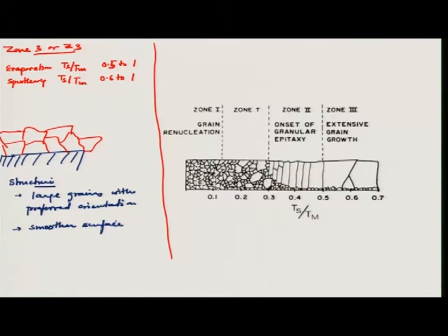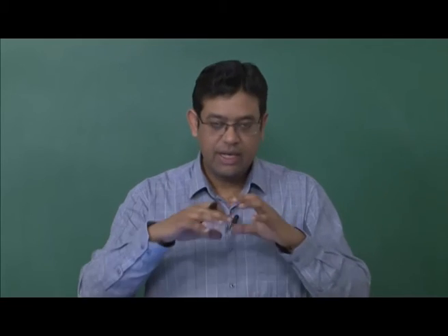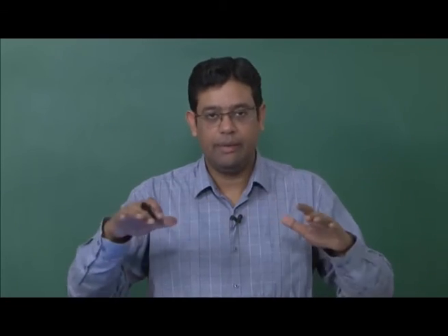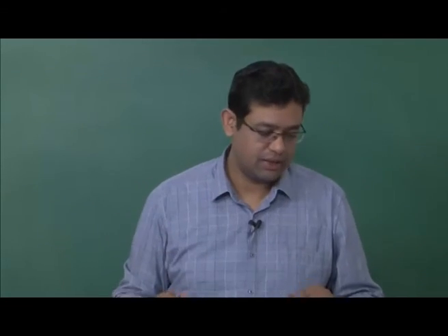because of surface diffusion, the material will try to diffuse, and the grains will start to coalesce, as we had discussed in the previous lecture, and they will try to form necks, and then due to the sintering effect also, the material will go into the neck region and give you a much smoother surface.